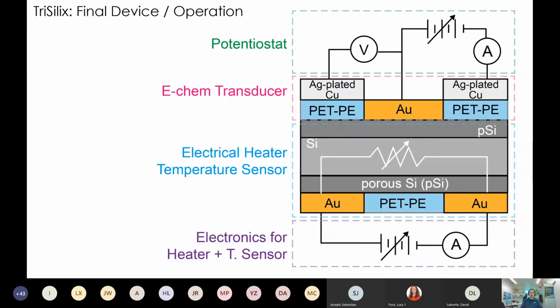And then we have the silicon material itself as the heater and the temperature sensor. So we basically don't need to add any other functions to implement a temperature sensor or a heater. And then at the bottom, we have 2 electrodes through which we can pass a current through the device itself, and at the same time, measure the conductivity of the device to see where it lies in terms of its temperature. And we need some electronics, obviously, to operate the device. To operate the electrochemical cell, we have a 3-electrode potentiostat, and to heat up the device and to sense its temperature, we have some electronics that are connected to the bottom 2 electrodes.